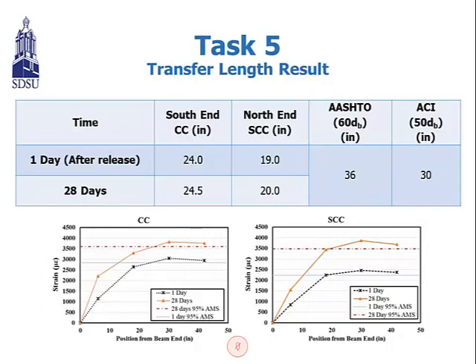And here's the transfer length result. We measured the transfer length after release for the SCC girder and the CC girder, and also at 28 days. You can see the SCC girder has a 19 inch transfer length and a 20 inch transfer length. On the other hand, the CC has a little bit higher than the SCC, with lengths of 24 and 24.5. And also we compared the result to AASHTO and ACI. We got a smaller value than AASHTO and ACI. Also you can see the graph for CC and SCC.